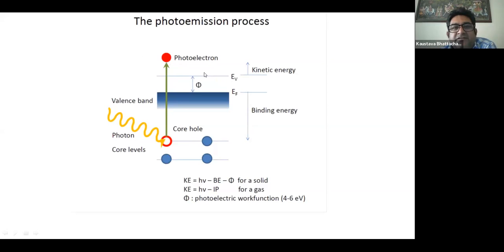This kinetic energy of the photoelectron will be equal to the energy of the X-ray that I have emitted, minus the binding energy of the electron, that is the energy with which it was bound, minus the work function, that is the energy required from the Fermi level to the vacuum level, which is particular to a particular element. So the kinetic energy is equivalent to the energy of the X-ray source minus the binding energy of the material minus the work function of the material.